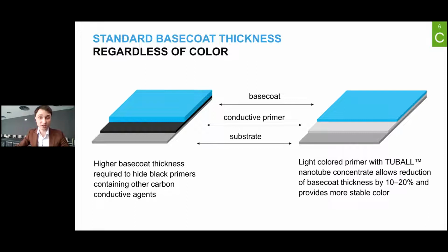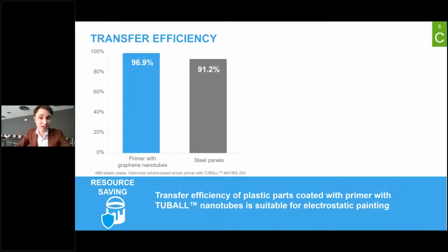What is crucial to add is that today it is possible to create conductive primer not only for polypropylene substrates, for example polypropylene bumpers or trims or other exterior parts, but also for SMC exterior parts. And the initial trials have shown that it might even be possible to assemble an SMC part coated with the primer with the metal body and paint it at the conveyor. So we have such an ongoing project, and if you are interested, we'll be extremely happy to discuss it more precisely separately. Single wall carbon nanotubes provide very good conductivity of the primer, which performs extremely well in terms of transfer efficiency. On the slide, you can see that even in comparison with steel, transfer efficiency is very high.